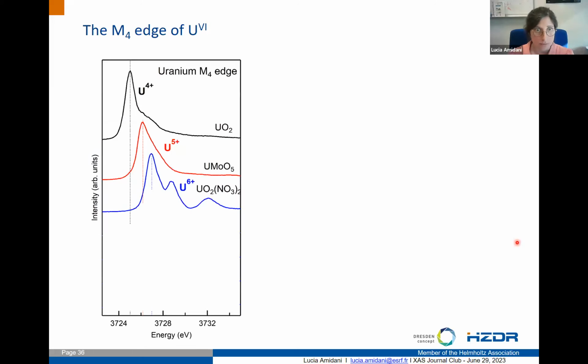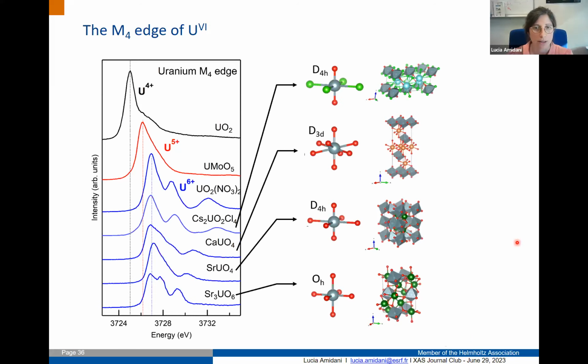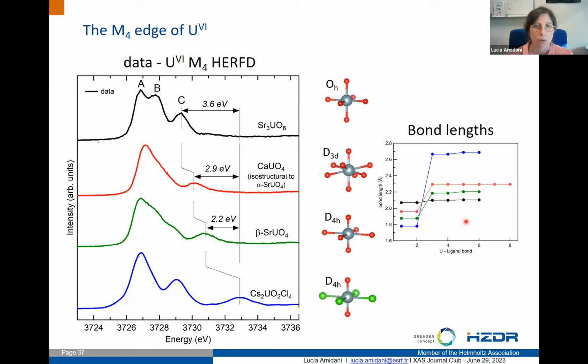So what about the data? First, just to verify they are all 6+, we put our M4 edges below the references, and we see that they nicely align towards the edge of the 6+. Looking closer at our samples, we notice the structure of the spectra are very similar: a main absorption edge, then a series of peaks. In the case of uranate and uranyl there are 3 distinct peaks, which we can call A, B, and C.